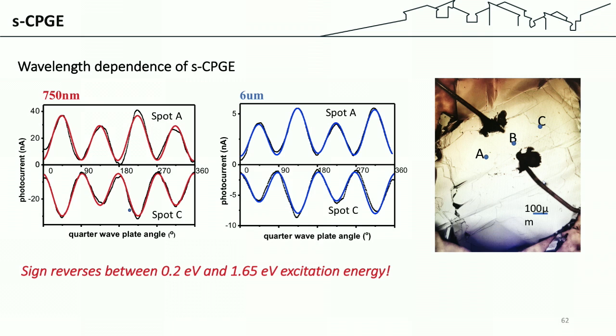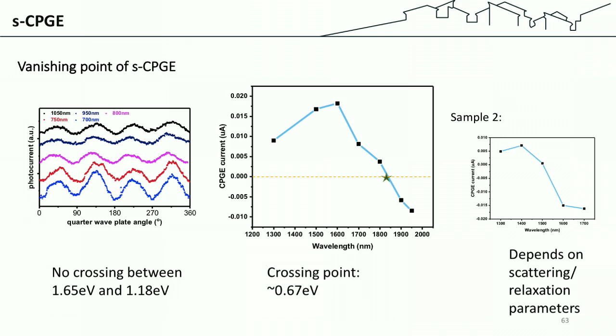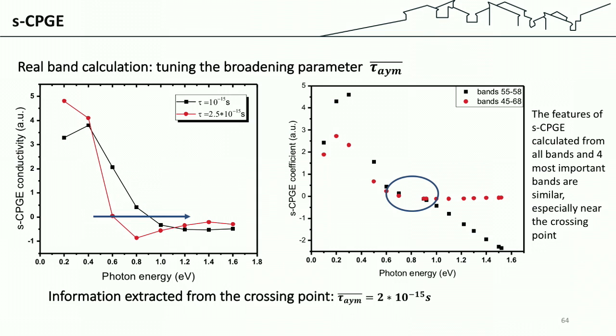And we've experimentally measured this recently. At high energy excitation, if we fix the spot size and the polarization, then the current circulates clockwise. But with the same spot size, spot location, and polarization, just by changing the wavelength to low frequency, the direction of swirling changes. Which basically means the bands are inverted. All that information can be extracted. By doing this wavelength dependence, it's now a spectroscopic technique, and by finding the spectral region at which this inversion from swirling in one direction to the other takes place, we can extract the asymmetric carrier relaxation time quite reliably. So from here we can extract microscopic parameters.